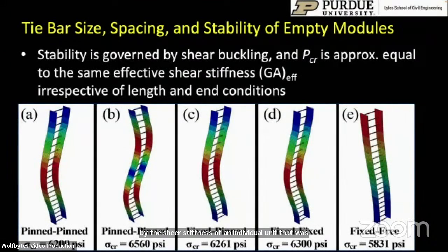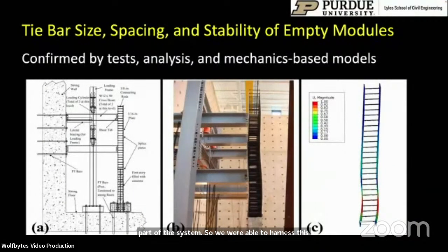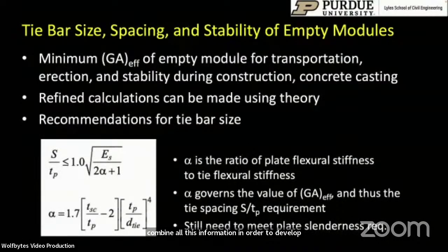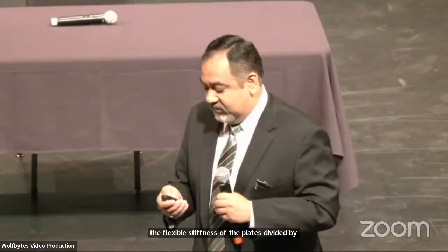So we were able to harness this understanding and develop equations for predicting the stability of this empty steel module. And research, you just saw the testing that had been done by my colleagues earlier, that experimental data combined with numerical models, we were able to combine all this information in order to develop simple recommendations for the design of this system as an empty steel module in order to have adequate stiffness and strength during concrete placement. So this minimum GA effective is now part of the code recommendation. So when the AISC 360 specification 22 comes out, you will see that it provides a tie bar spacing divided by plate thickness limiting equation, which is based on the shear stiffness of the individual empty module, which is a function of the flexural stiffness of the plates divided by the flexural stiffness of the tie bars. It's pretty fascinating.